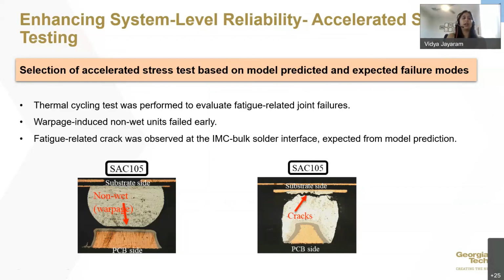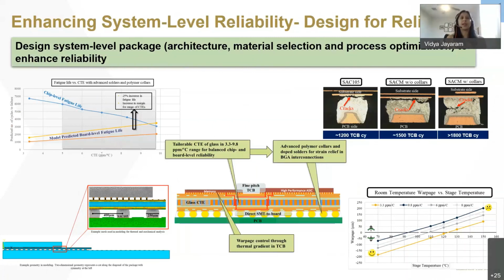Now, at this point, we had to design a system to extend our system level reliability, considering the chip level defects and the board level defects. So we used the approach for package architecture, material selection, and process control. So the first part was to model this 2.5D system to check for chip and board level fatigue life as a function of the glass CTE. So we used the property of glass with tailorable CTE to check for what CTE would be optimum to have a balanced chip level as well as board level reliability, since they're both going in opposite directions.